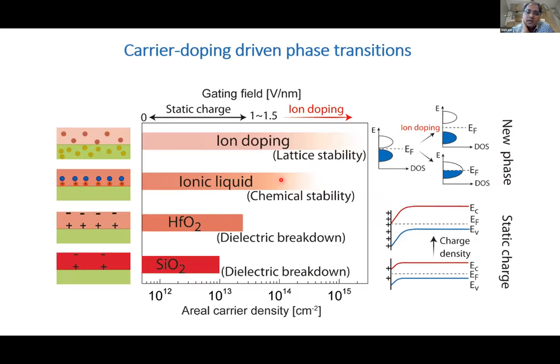So the physics of this is related to the doping mechanisms. We are very familiar with traditional gate dielectrics for band semiconductors like silicon. And this is the first slide I showed. Basically you're moving the position of the Fermi level with respect to the band edges, and you have typical electric field effects. You could extend this by maybe an order of magnitude with just the right semiconductor using electric double layers.